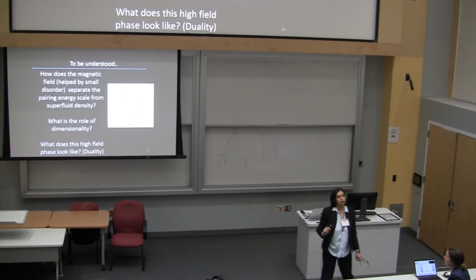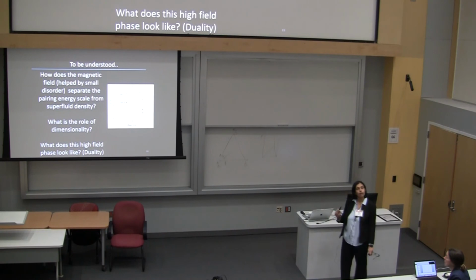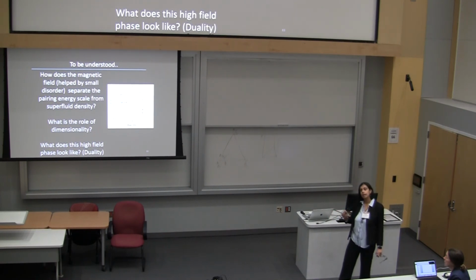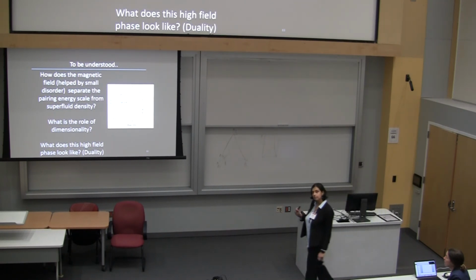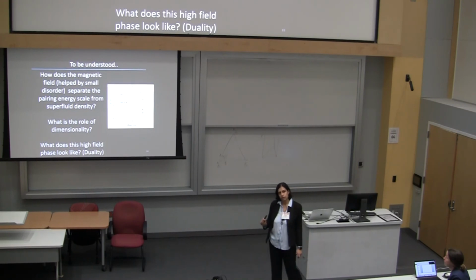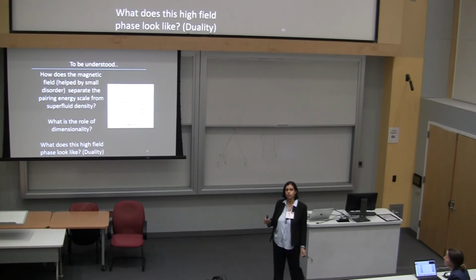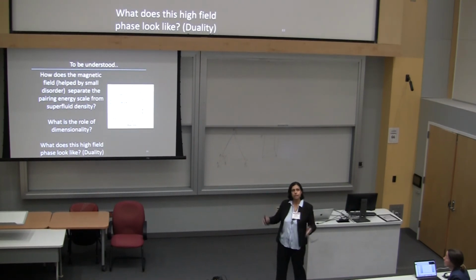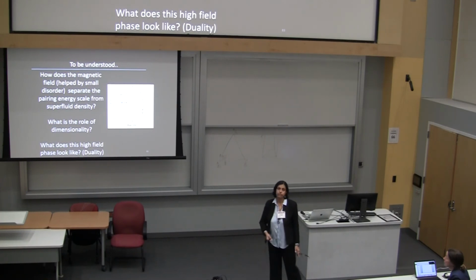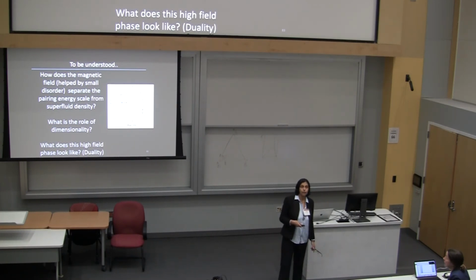I'm going to stop here. So basically, we have a mystery. We have a pseudogap in the system. We don't have a huge amount of disorder. We have a little bit of disorder. We know that because the coherence peaks aren't very large, and the bottom is a little lifted, even at 300 millikelvin.